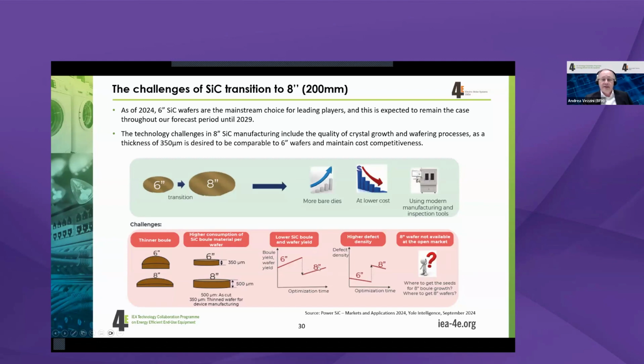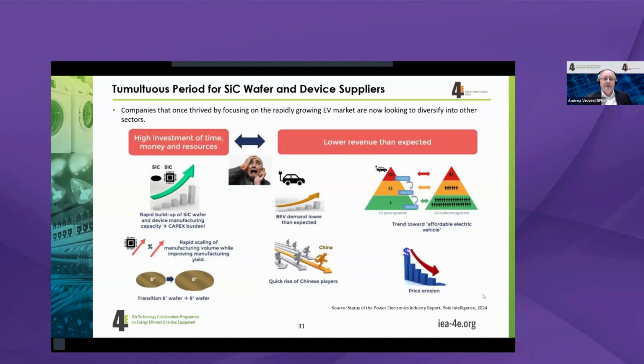But on the other side, as you can see here, this is their problem. By changing now from 6 to 8-inch, they're starting again with the yield optimization. They're starting again with the defect optimization. And apart from Wolfspeed, some of the bigger players are still a little bit waiting on investing, because the transition is a big issue. But in the coming period, we certainly see this move. This is also a little bit pushed by a quick rise of Chinese manufacturers of silicon carbide, given by the demand of the local market.